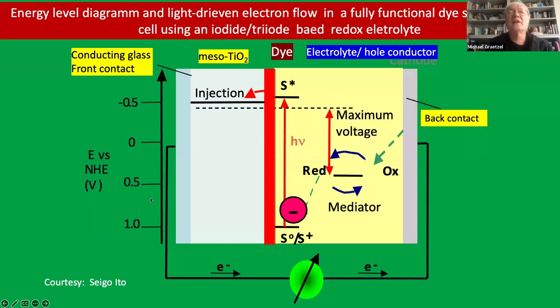Now let's just look at the energetics for a minute. So we have the excitation by light, the electron is injected, goes in the external circuit, comes back, and now we have to shuttle it back to the sensitizer. So you need some kind of a redox shuttle. It could be a solid-state hole conductor or redox couple. Initially, we used iodide and iodine. And that was not a good choice from the energetic point of view, because you can see that half of the photon energy was lost in a regeneration reaction. So in other words, the oxidized dye gets reduced back to the starting state using iodide. However, the energetics are not very favorable for photovoltaics, and so there is a big voltage loss.